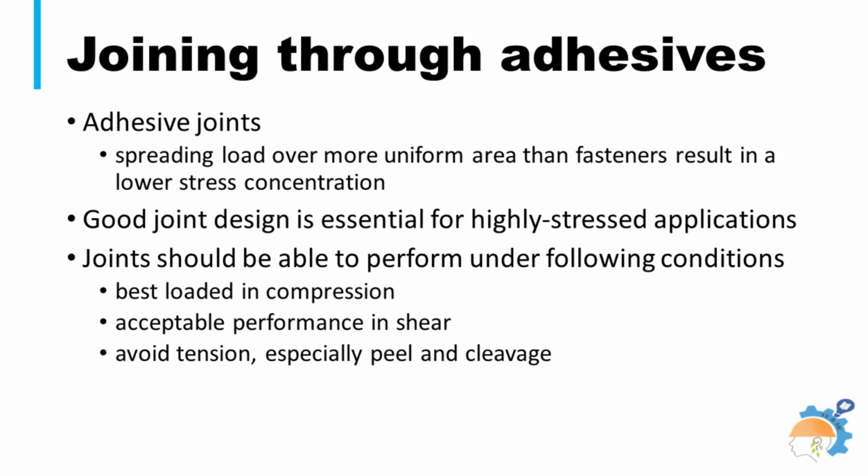In general, bonding between two composite layers is achieved in the presence of an oxygen-inhibited layer of unpolymerized resin. Epoxy adhesives are the most common adhesives for composites. Heat-curable single-component epoxies provide high-strength bonds to many composite materials.